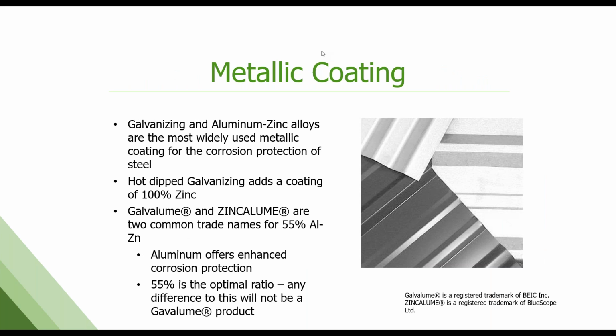So metallic coatings, I want to talk about this a little bit because it's really important in the final performance of the product. It's either hot dip galvanized, which is 100% zinc, or it's a 55% aluminum zinc product, also known as Galvalume or Zincalume in the industry. You've probably seen those names on common coated steel that's out there. Of course, we do coat aluminum as well. It has great corrosion protection. The Galvalume product, the 55% aluminum zinc product, is the next best for corrosion protection and does come with a substrate corrosion warranty from most suppliers, whereas your galvanized or 100% zinc product will not. A note here that Galvalume and Zincalume are registered trademarks, and you also have to be licensed by BEIC Inc. to call your product by these names. So it is a licensed product. Next slide.